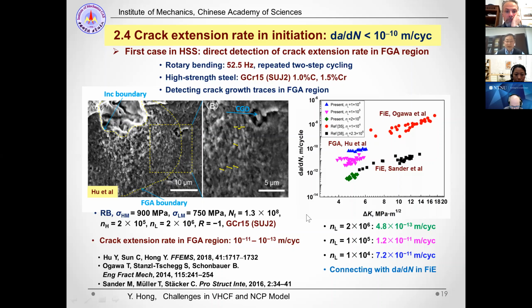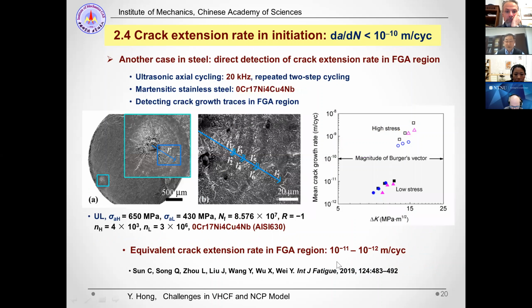This is step cycling for a stainless steel, and the results show that the data is between 10^-12 and 10^-11 meter per cycle.